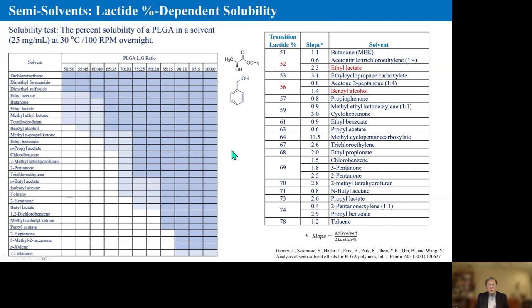So to do that, let me introduce the concept of the semi-solvent approach. A semi-solvent is basically a solvent that dissolves certain PLGA, but not all of them. So for example, dichloromethane dissolves all PLGA at any LG ratios. But let's go to, for example, toluene. By the way, the blue rectangles mean that the polymers dissolve in that particular solvent. White means the polymer does not dissolve in the same solvent. So if you look at toluene, LG ratios 50-50 all the way to 65-35 do not dissolve. But above 70-30 and all the way to 100, they dissolve.